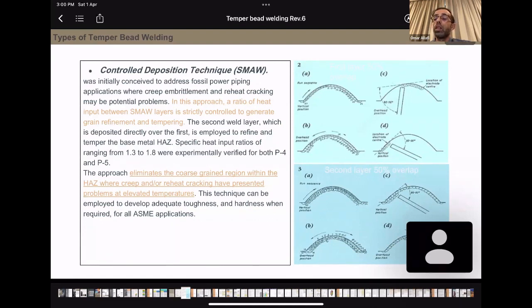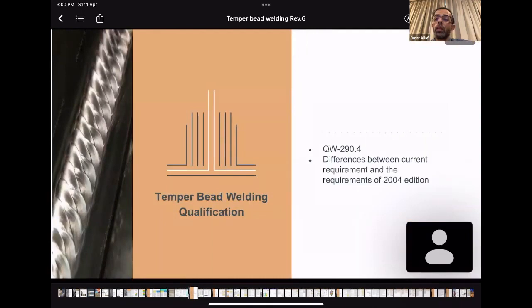So in this technique, again, you are controlling the heat input and heat input ratio, and you have an overlap percentage between the weld layers of 50% between the weld beads. So the differences between the current requirements and the requirements of the 2004 edition. We'll see how it was adopted for the first time in ASME Section 9 in 2004.